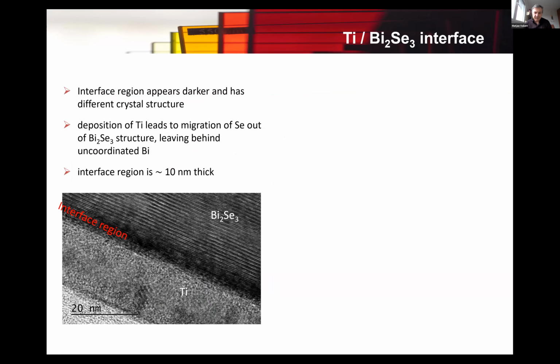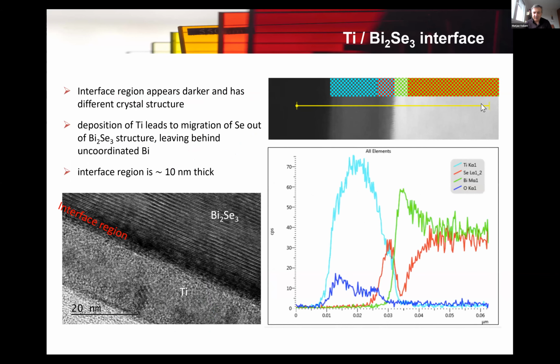Okay, we have done more analysis. This is TEM analysis, and chemical profiling over the cross-section has confirmed again a layer on the interface, a layer of titanium selenide, followed by a layer of metallic bismuth. And then we go into the bulk composition again. So there is no doubt that this interaction is significant already at very low temperatures.